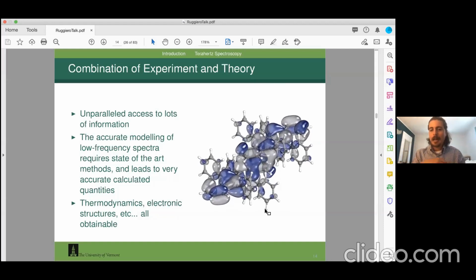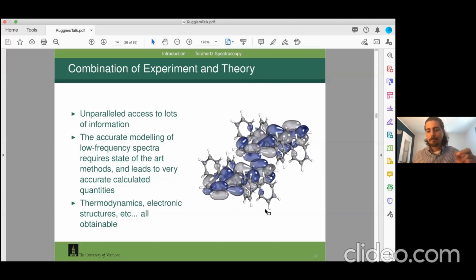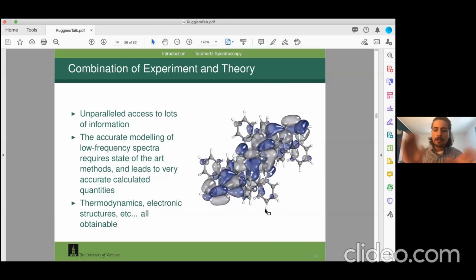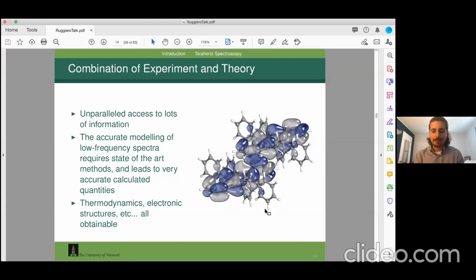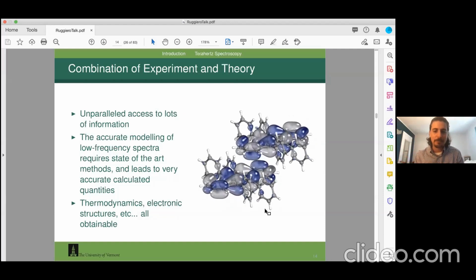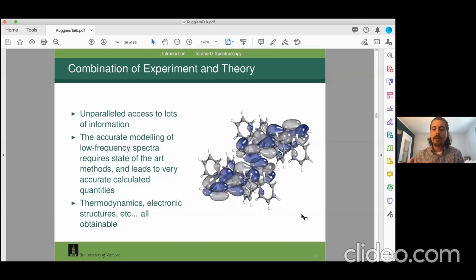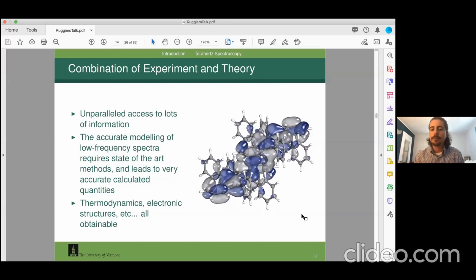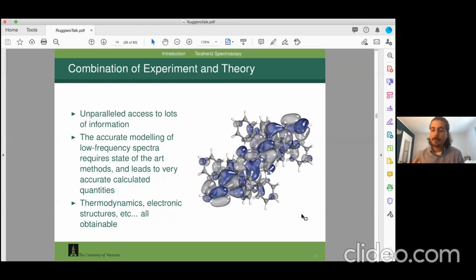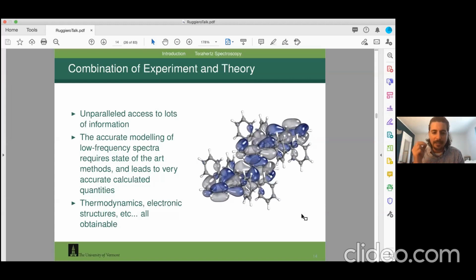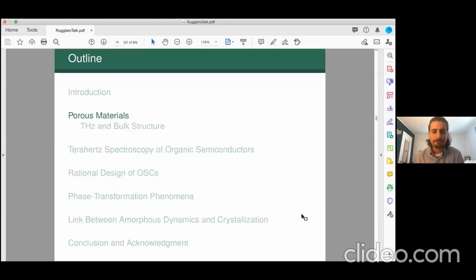So if I do my terahertz experiment and I do my theory and everything matches, I can trust my thermodynamic parameters, my Gibbs free energy, the entropy, enthalpy, all of this, without going and doing thermodynamic experiments, because it has to be right. If the vibrations are right, the thermodynamics have to be right. That's where some things that we've done, where we've predicted the stability of polymorphs, really shine, because we can use all of this together to get some really important information.